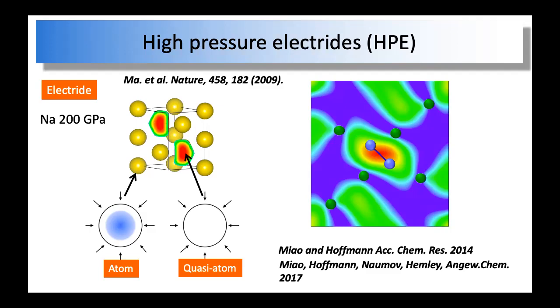So what's behind that? Well, from the quasi-atom point of view, it's much easier to understand, because if you observe, those two singly occupied quasi-atoms are very close to each other, with a distance of, I think, 1.3 or 1.4 angstrom, and they form a strong chemical bond. We can even identify the wave function of the bonding states, and also the anti-bonding states, which very clearly show that.